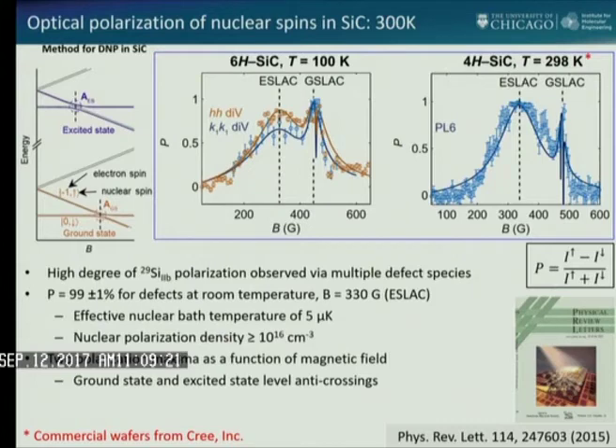So I can't tell you how rare this is in nature. For people doing MRI, for example, in hospitals, you have these very large magnets, right, when you do an MRI image, and it's because the effective polarization is a tiny fraction of 1%. That's what happens with MRI, very tiny fractions for imaging. So here, with a few hundred Gauss field, which is extremely low, you can get 100% polarization at room